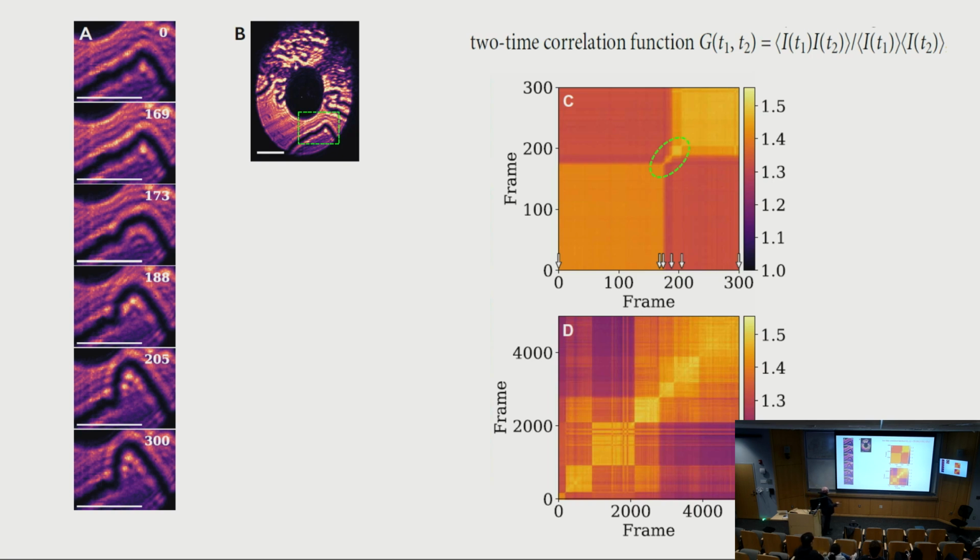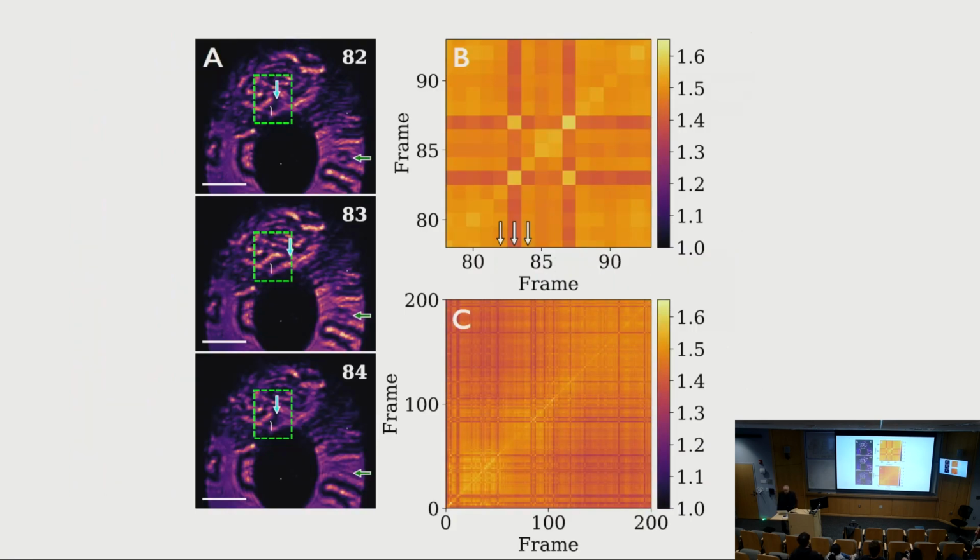If you calculate the two-time correlation function over many, many frames, as shown here, you can make several conclusions, and one of them is that you see squares of this type, squares of larger type, lines of a smaller size. This observation is telling us that in the particular fluctuating region, various time scales are present. You go from the lowest time scale that we can resolve, in this particular case 0.1 second, to many minutes. So things are fluctuating on various time scales near the phase transition, actually as expected.